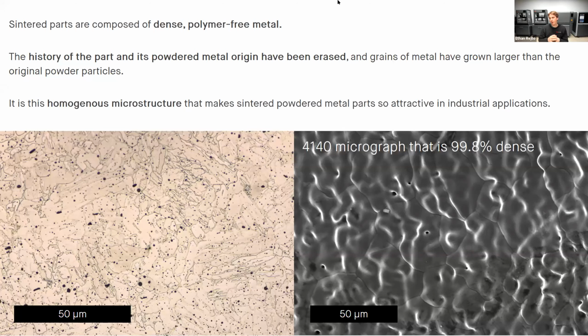Sintered parts are composed of dense, polymer-free metal. This is very important. After the sintering process, there is no history that the part was ever powdered metal. It's been completely erased because we're able to raise that part slowly to its sintering temperature, where we're actually able to have some grain growth. The grains have now grown larger than the original powdered metal particles were, and there's really no history that the part was ever powdered metal.